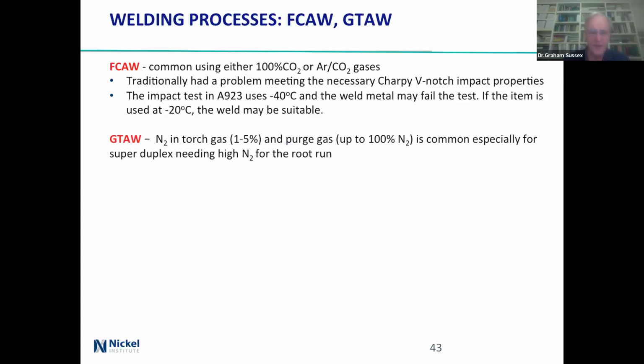GTAW or TIG: nitrogen in the torch gas, yeah, that'll help, 1 to 5%. Purge gas: if you're looking at a piece of pipe, you always have purge gas, and hey, it always helps if you've got it, because the root is absolutely likely to get most of the corrosion problems. And so you put some nitrogen in.